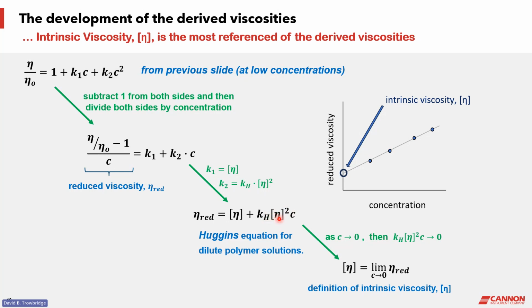And you can look at this equation and realize that as the concentration goes down, as it even goes to 0, the second term will go to 0 because the concentration will drive the significance of all of this to be negligible. And what you're left with then is simply the reduced viscosity is equal to the intrinsic viscosity. And this becomes the definition of intrinsic viscosity. In mathematical terms, we say that the intrinsic viscosity is the reduced viscosity in the limit as concentration goes to 0. So that's significant because it gives us a method for analyzing and determining the intrinsic viscosity using Huggins equation. Graphically, it looks like this. You'll make several measurements. Here's 4 measurements shown.